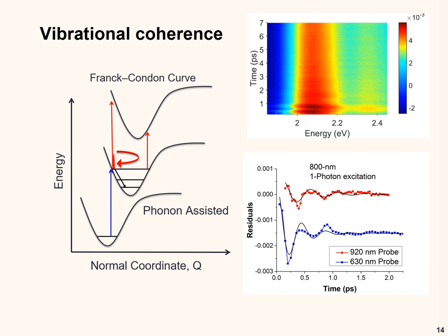For example, we promote electrons from the ground state into the excited state, generating a superposition of electrons in the excited state. When we probe different channels, they will have vibrations on these two different probing channels, and also have this pi phase shift. This is like stimulated Raman spectroscopy. People have done this, but it's the first time we observed this vibrational coherence in a gold nanocluster.